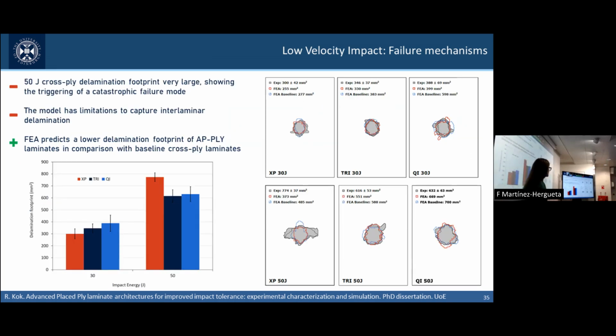When we evaluate the performance, we mentioned that all the laminates were behaving pretty much similar. When we evaluate the delamination footprints, that's something that we can also find. They all present a rather circular or elliptical footprint, except for the cross-ply laminate impacted at 50 joules that has a much larger delamination extension here with a cross-shaped footprint. This means that the catastrophic failure mode that we activated and we mentioned before is delamination. Our numerical model, unfortunately, couldn't capture that failure. There is a reason for that.